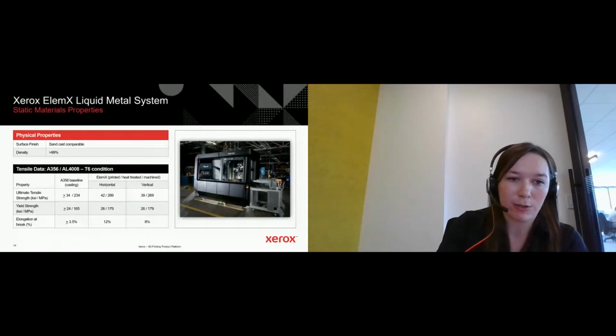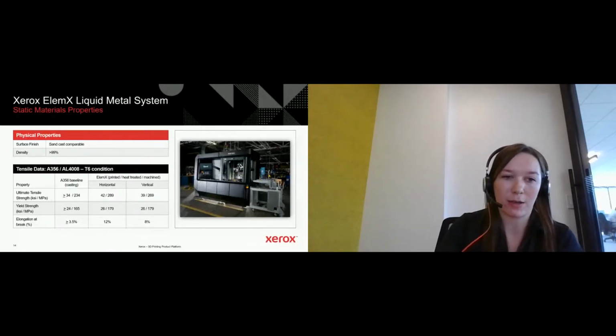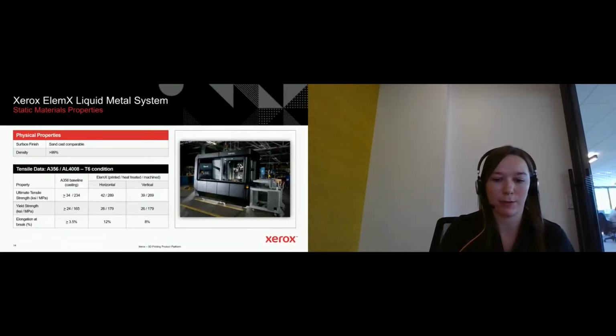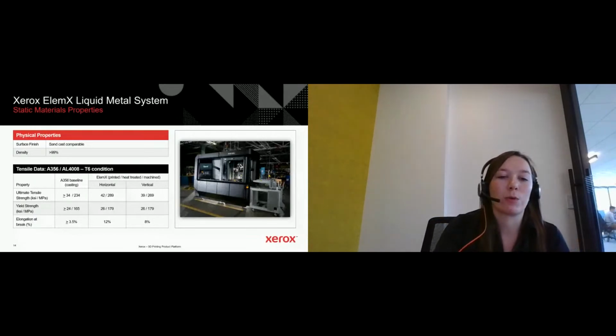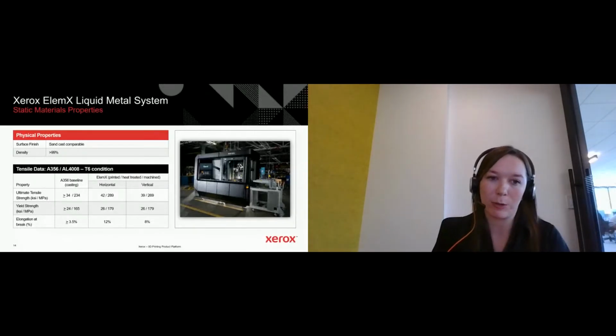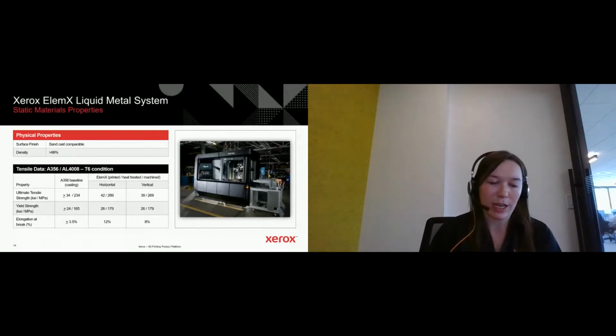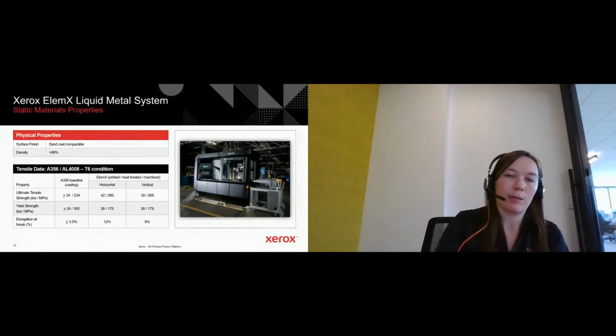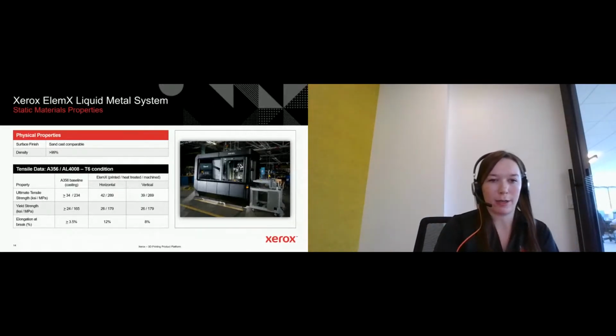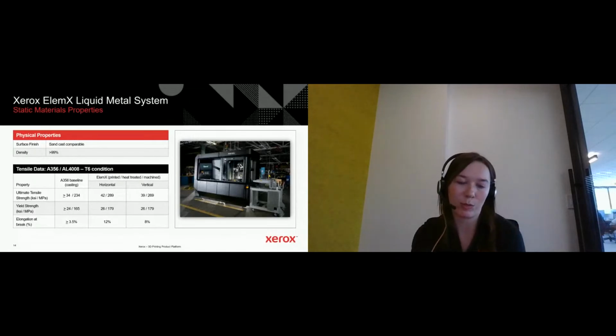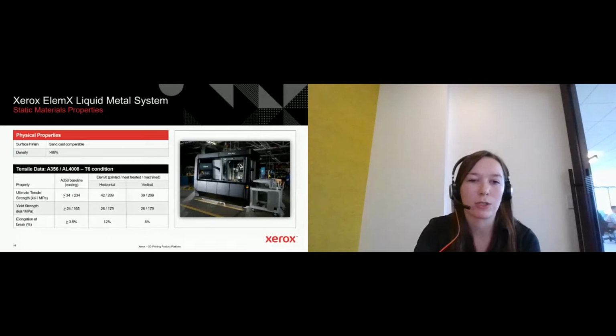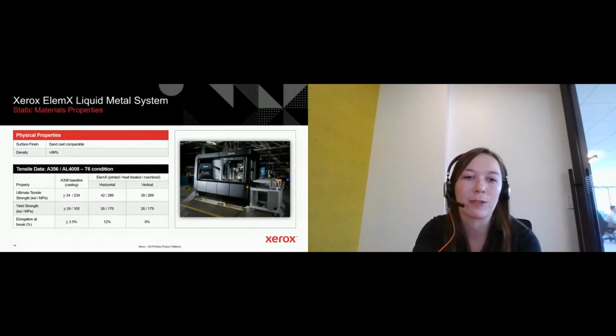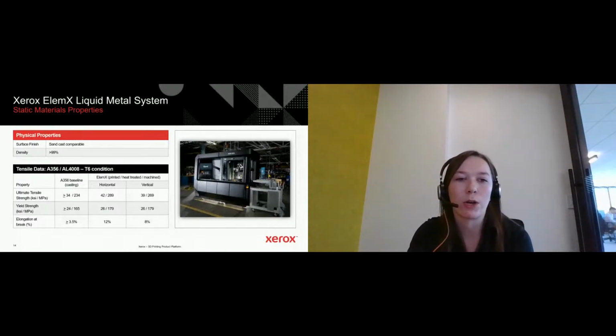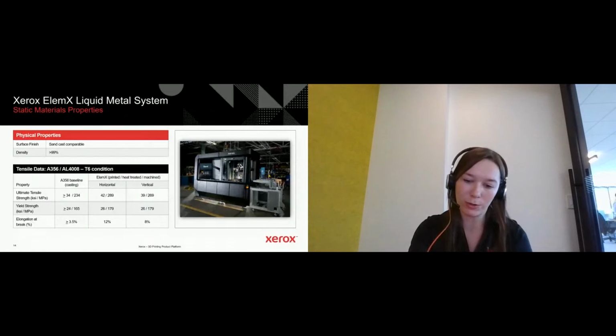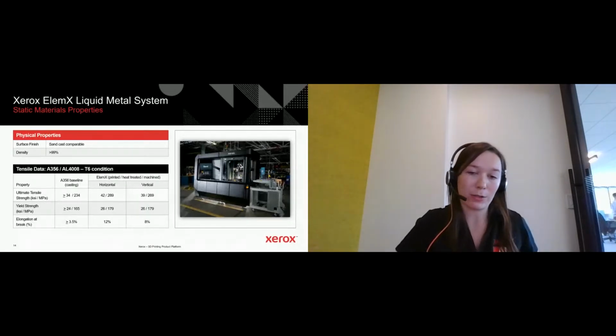And then you'll see some tensile data. So on the left, we have a baseline for A356 sand casting from the ASTM standard. And on the right is what we've achieved in printing. So this is still first generation technology. We're still developing. But as a metallurgist, I'm pretty happy with these numbers. We're above the baseline. Especially the elongation is pretty good. We do, of course, see some differences between horizontal and vertical orientation, which I think is fairly standard for the additive industry. But of course, we are working to understand what drives those differences and how we might improve our printer to improve upon those differences.